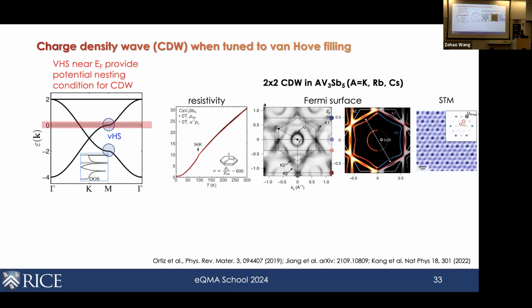By flashing the results people have observed in these AV3Sb5, or vanadium-based Kagome systems, which only have a charge density wave order. As a flash in the beginning, we expect, at least in this idealized picture, if you tune the chemical potential to be at the Van Hove point, we expect this kind of Fermi surface, and this will give you a nesting that would correspond to this 2x2 in-plane charge order. That's been observed in the AV3Sb5 system, and this is the experimentally measured Fermi surface. There's some deviation, but you can largely see some agreement with this picture. And the charge order has also been observed by STM and many other kinds of probes.